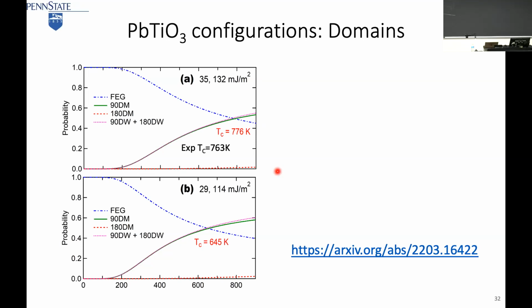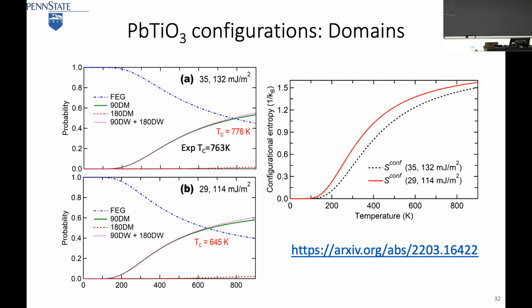If you do the statistical mechanics, you cannot relax. We talk about that in the next slide. And then we can predict the entropy. The entropy is very, very huge, in fact. 1.5 kB is huge. It's kind of crazy.